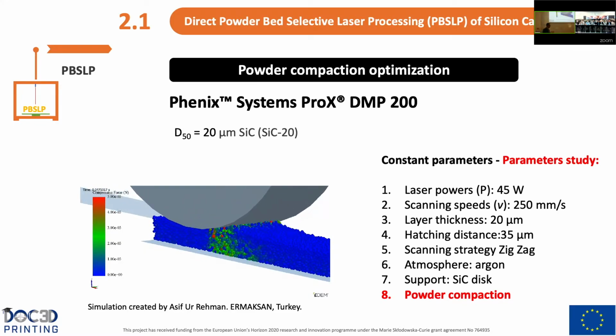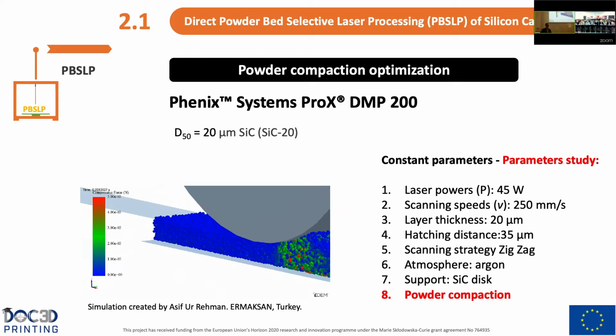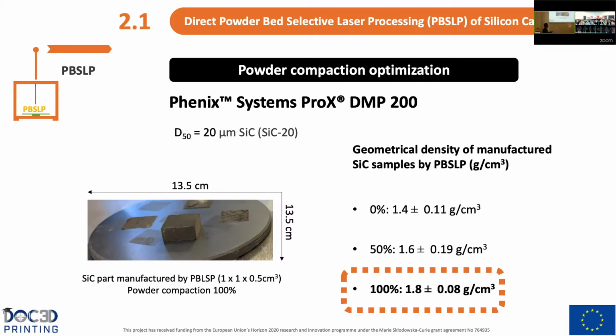To do this, we measured the geometrical density of the sample after the manufacturing process. So here, we use 3 different powder compactions. Here, 100% means that, for example, if the layer thickness in this specific case is 20 micrometers, we compact the whole layer thickness, 20 micrometers; here 10 micrometers, and here nothing. And we obtain the best results in terms of geometrical density with 100% compaction.